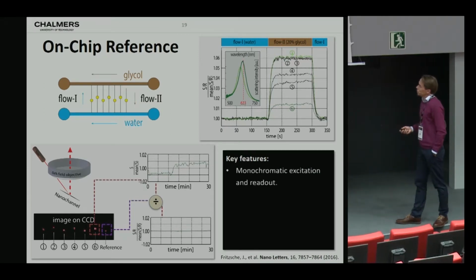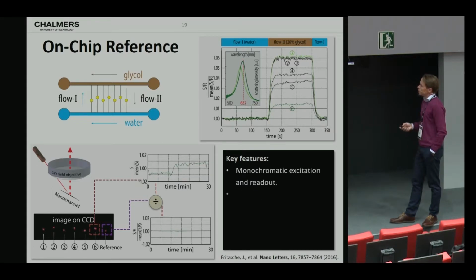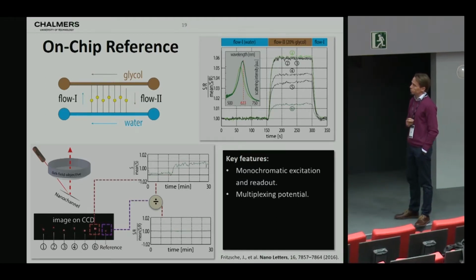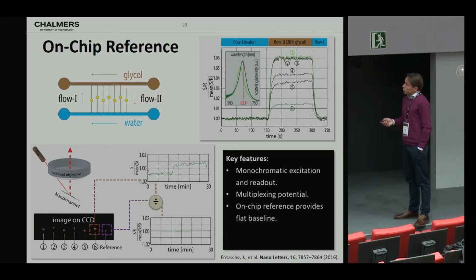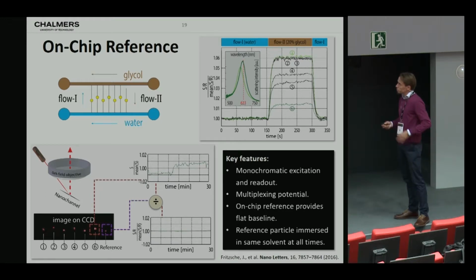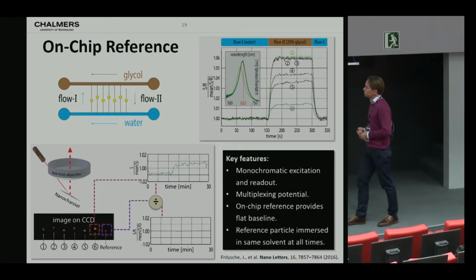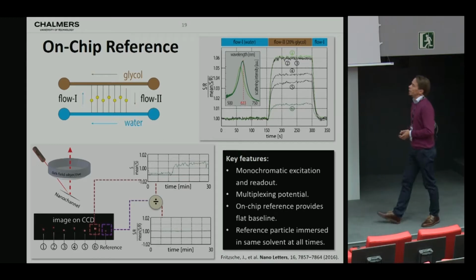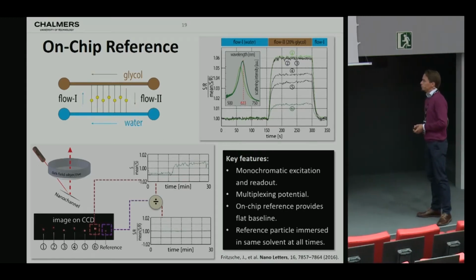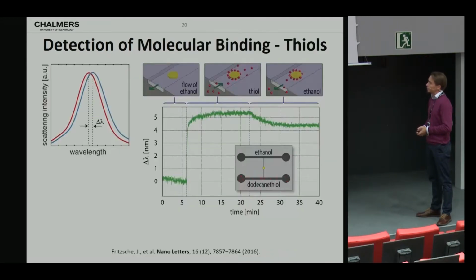What do we learn? Well, we can use monochromatic excitation and readout, which is very interesting if you want to do multiplexing and look at many particles at the same time in their individual fluidic systems, because you don't have to, for example, employ hyperspectral imaging. We have this on-chip reference, which provides a very flat baseline over long periods of time, and the reference particle is essentially immersed in the same solvent at all times, which is a significant advantage if you want to do sensing.